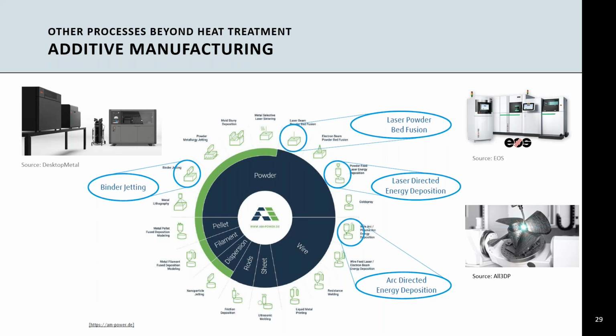In this process, the powder is contained in a carrier gas and directed to the substrate through a nozzle, which is concentric with the laser beam. Alternately, a wire can be fed from the side as well. The powder or wire is melted to form a deposit that is bonded to the substrate and grown layer by layer. An additional gas jet concentric with the laser beam provides additional shielding or process gas protection. The method is suitable for large components where a higher deposition rate is required.